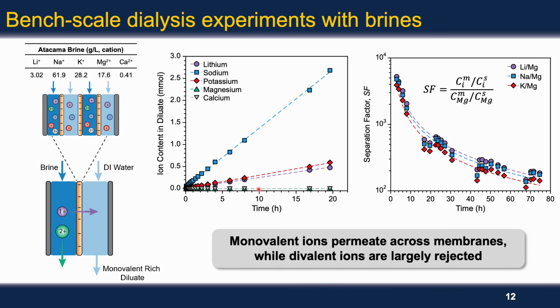We can calculate separation factors of the monovalent ions with respect to magnesium, and we found that initially these values are greater than about 5 or 6,000, and then they decrease as a function of time. And this decrease is largely because the magnesium transport becomes faster as that concentration gradient within the membrane shifts. Nevertheless, these results demonstrate that this process can achieve exceptionally high separation factors under realistic brine conditions, and these values are substantially higher than those of typical nanofiltration or electrodialysis experiments at comparable conditions.